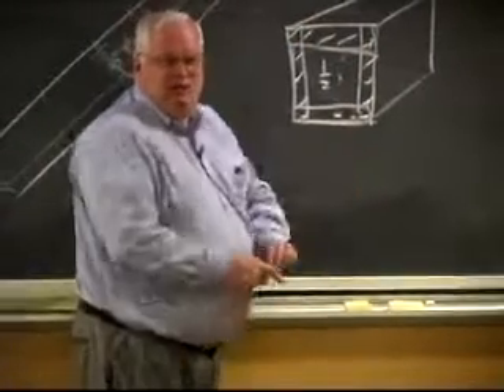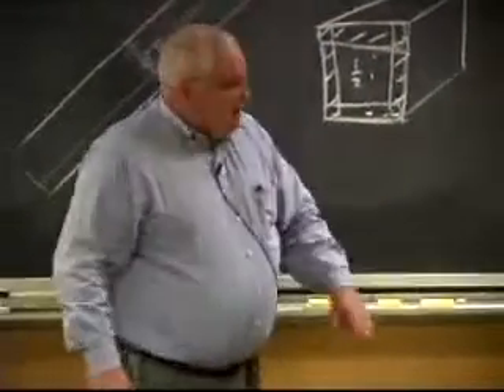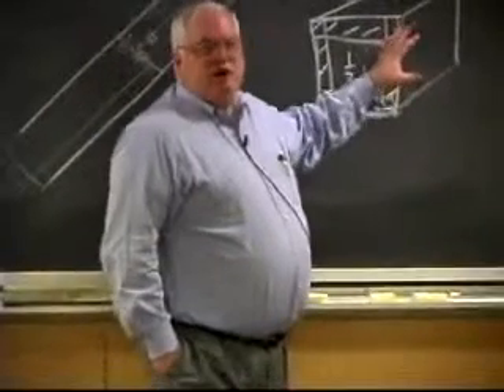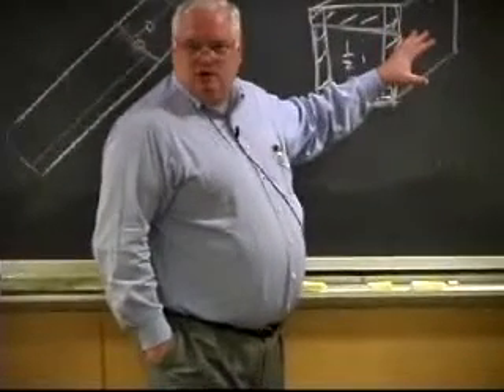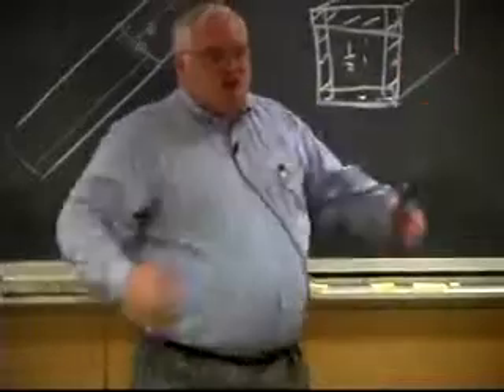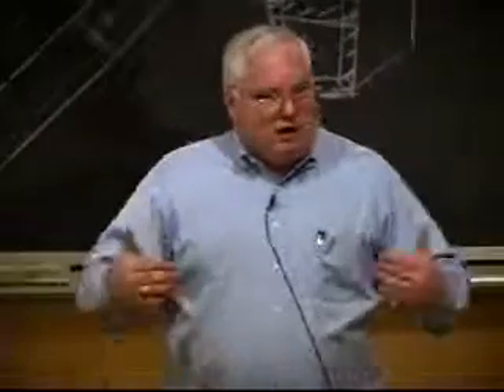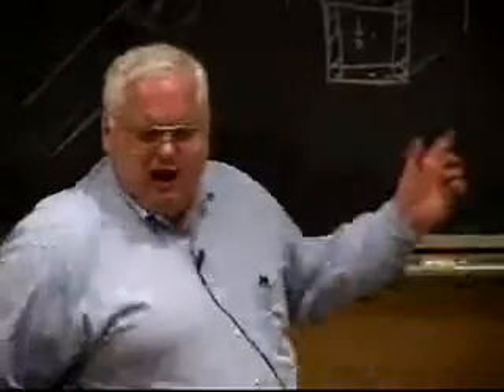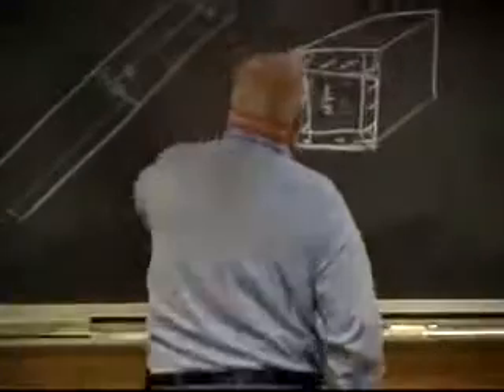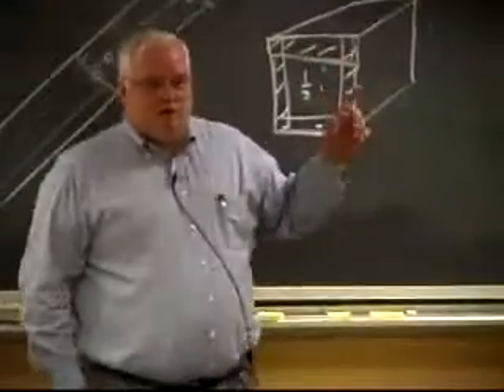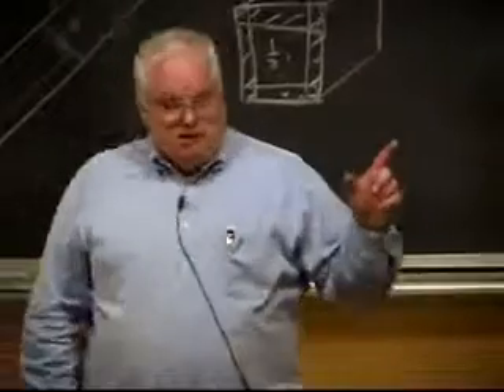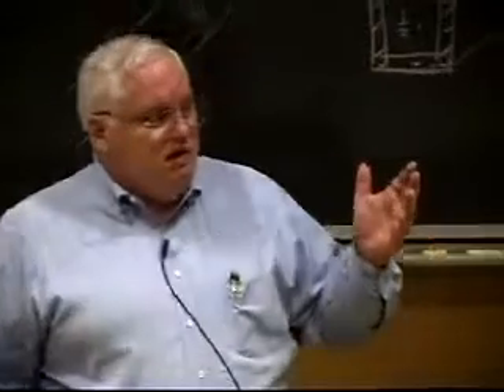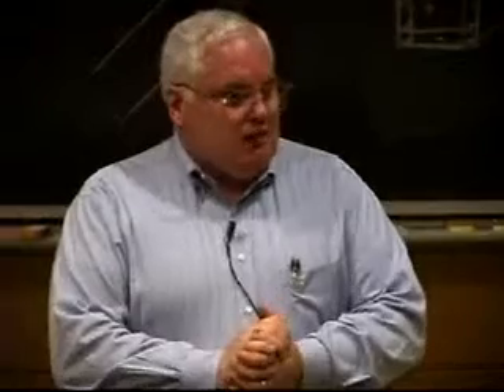So what does that say about the design? It says this is a deflection limited structure. This is not a strength limited structure. You want it stiff so it doesn't bow and everything like that, but you don't need the strength. I mean, calculate the strength of a 1/4 inch aluminum weld 4 inches long. Okay, 4 inches, it's 1 square inch. 1 square inch at 20 KSI, the thing will support 10 tons. I'm just putting electronics in there. How much does it weigh, right? So it clearly was a deflection limited design.